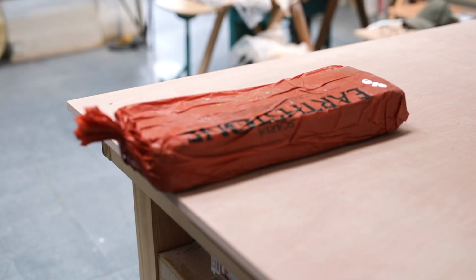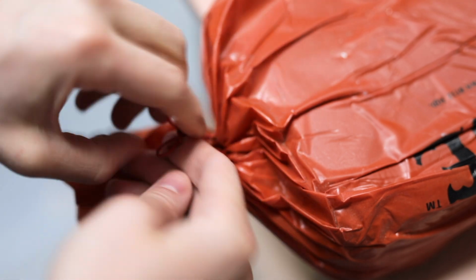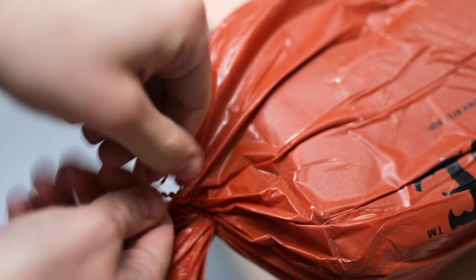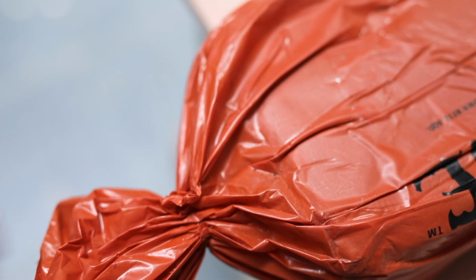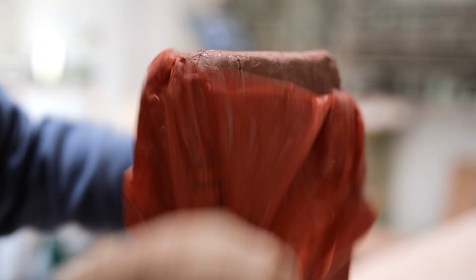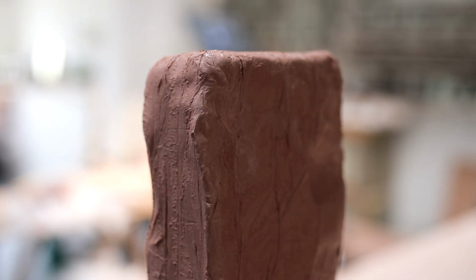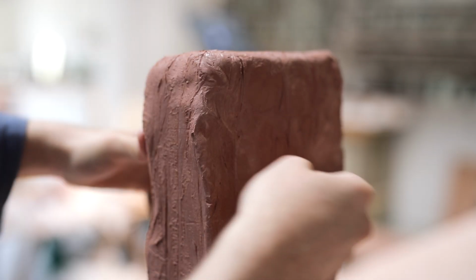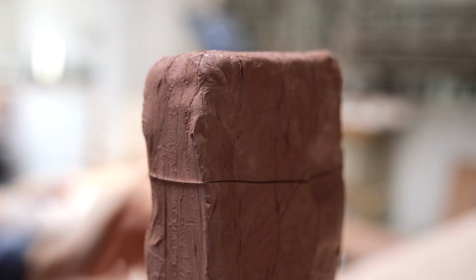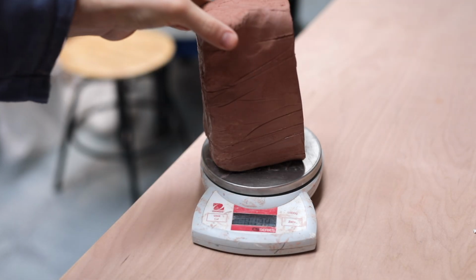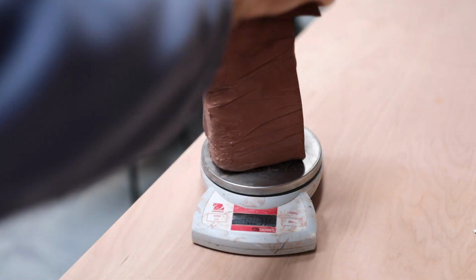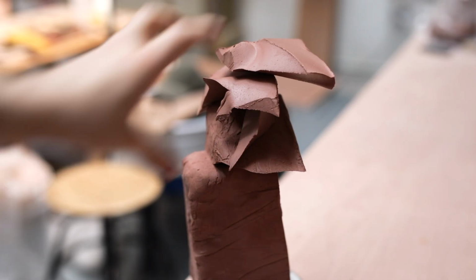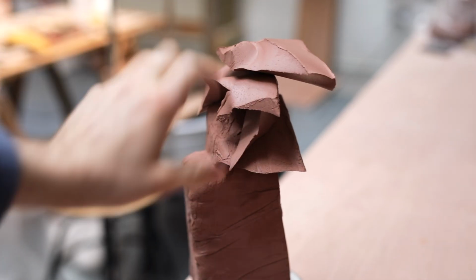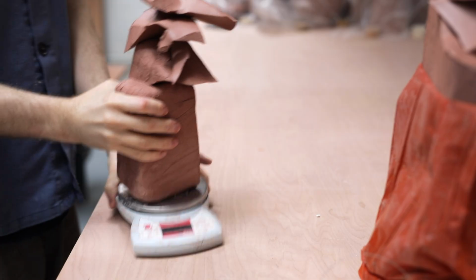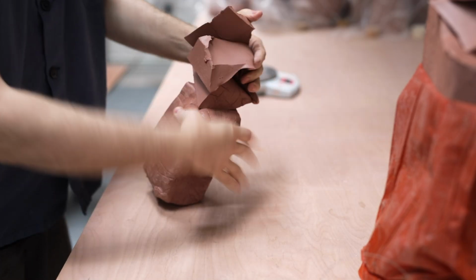This clay is called Earthstone ES80 and it's manufactured to be reduction fired, or at least that's when you'll get the best results out of it. If you fire this body in an electric kiln and in a normal oxidized atmosphere, it just turns a flat grey sort of tone, whereas if you reduction fire it in a gas kiln, it's far more rich and flecked with specks of iron, and it can flash nicely from where the flames come into contact with it. I used about 2.7 kilos of clay, which is about 6 pounds.